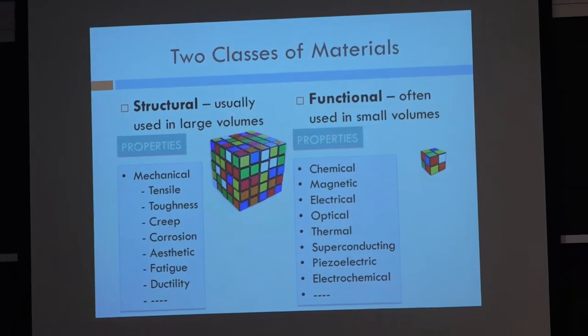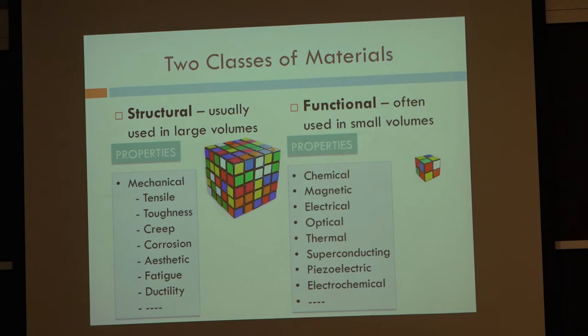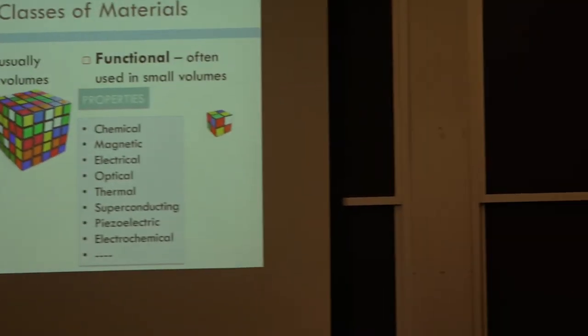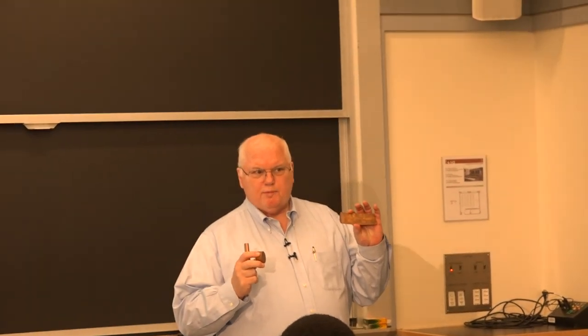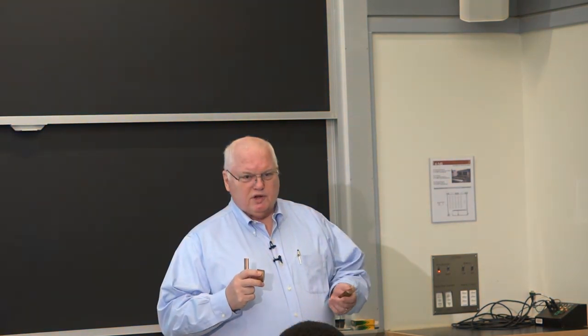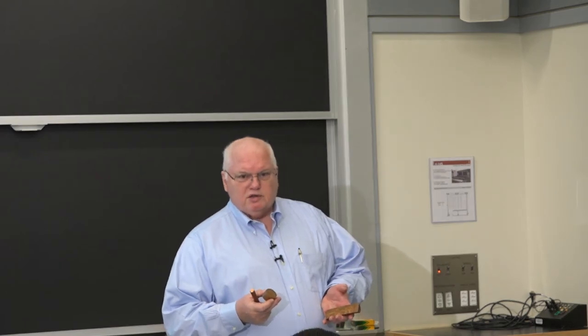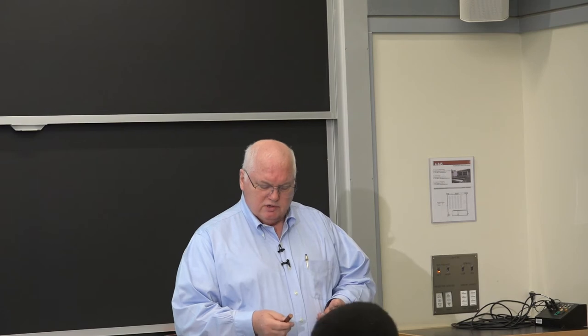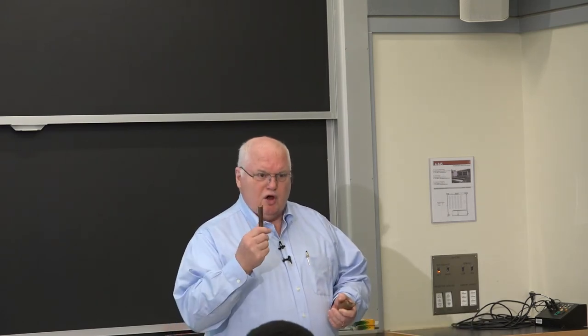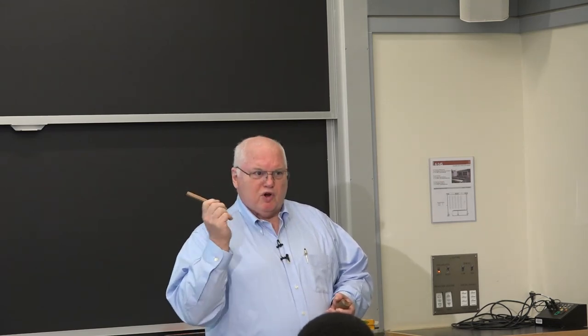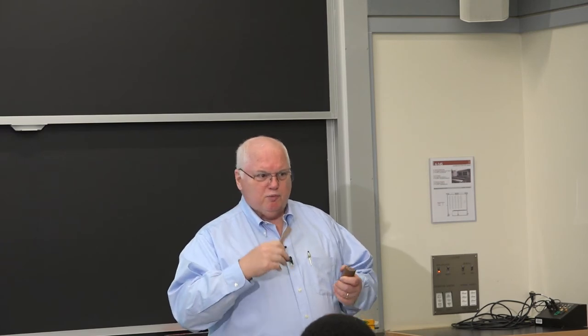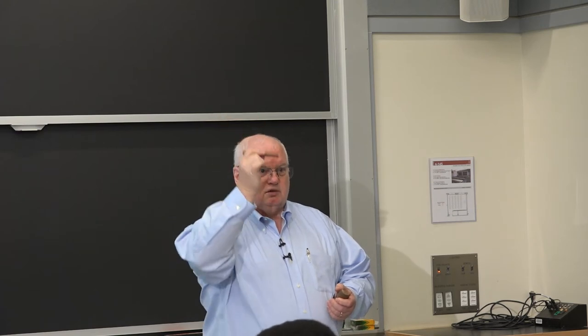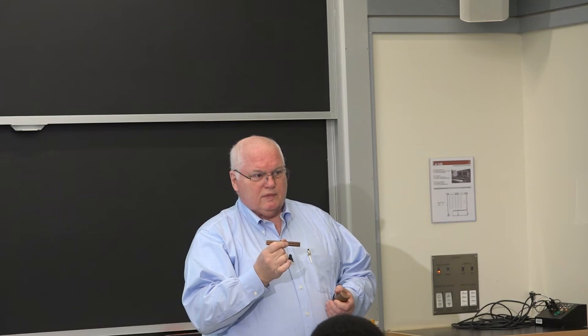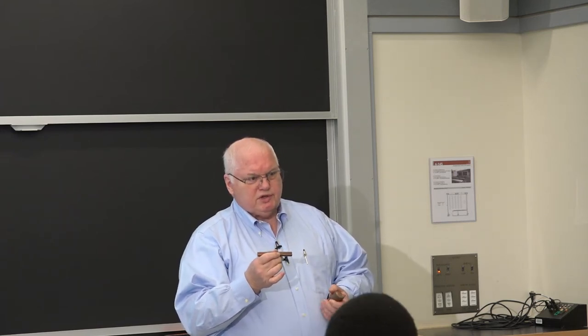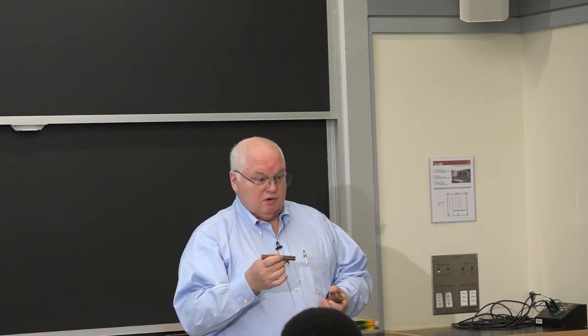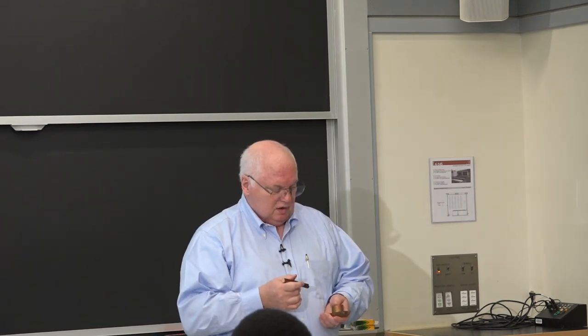Now, there are cases where you'd like to have a fine grain material for strength, and here's an example of that. This is copper. It's actually copper with just a little bit of silver in it, only 0.2% or 0.1%, to strengthen it. But it had very large grain size. And I was asked one time, I was given all of 48 hours to go to New York where they were making this, and they were going to draw it into wire for the Northeast Extension. If you've taken Amtrak and the Acela train between New Haven and Boston, they were putting in the trolley wire. This is the overhead conductor that basically carries the electric current. You need the copper for wear resistance, corrosion resistance, electrical conductivity, but it also has to be a structural material.